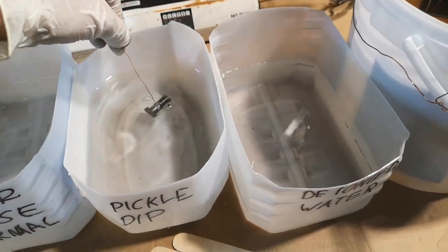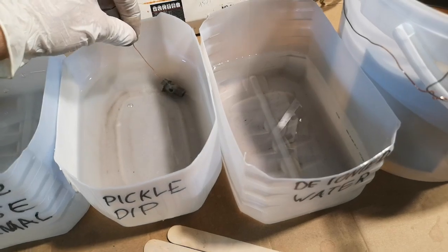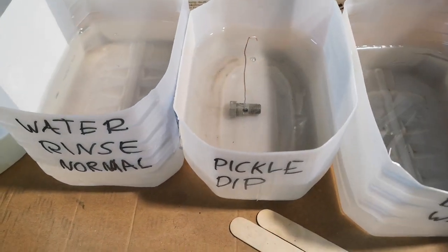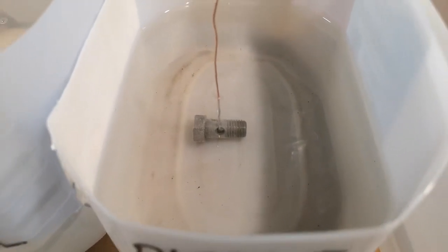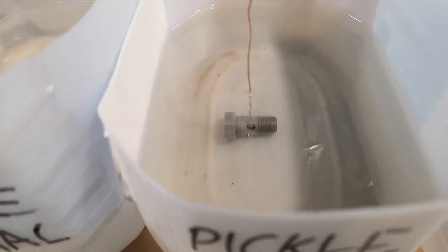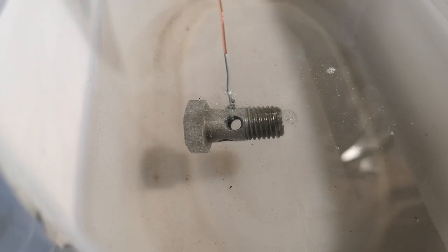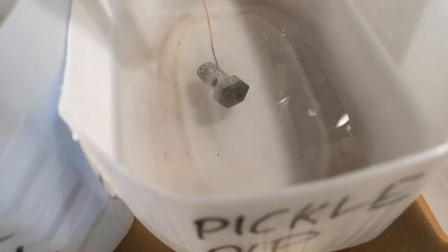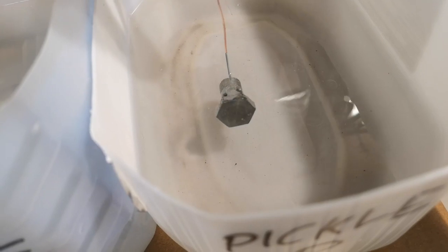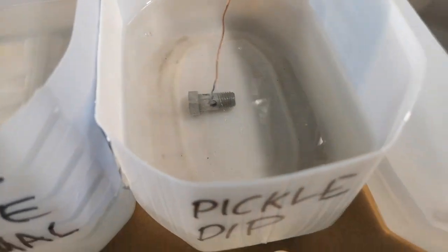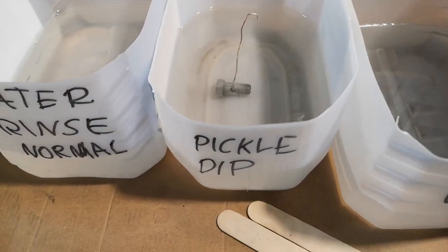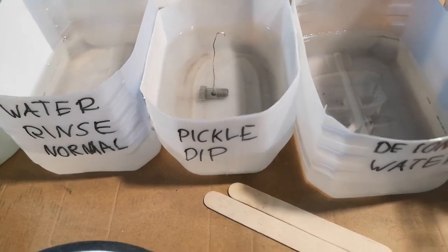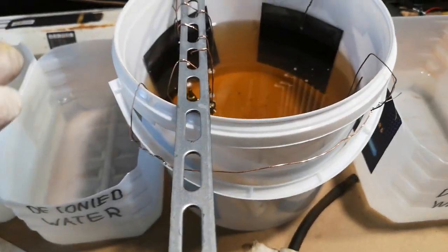So not to transfer one chemical into the other, then we put it in acid, which is called pickle dip or dry pickle dip. As the guys from Project Binky noticed, there's nothing dry about this because it's wet. As you can see there's a reaction there, which shows you there's actually contaminants on the surface. And as long as this reaction is going, you know that the part is not ready to go into the next bath.